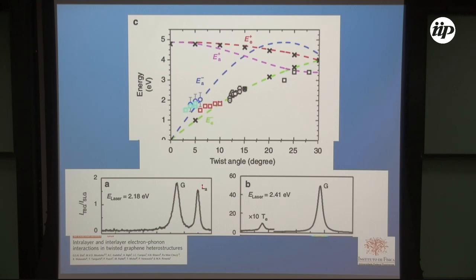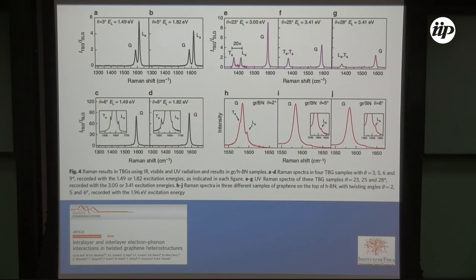So here, in this case, I have an LO phonon intralayer process. In this case, a TO phonon interlayer process. But you can have others also. My time is over, but I need to give you just one more case. When Eliel and Marcos did the calculation, they showed me, I said, well, that's very nice. But if this is true, now if you have graphene over boron nitride, you only see intralayer processes because you see only the process in graphene. So Eliel did the measurements for the boron nitride. The peaks are very small, but we can see only the intralayer process here when you have graphite over BN over graphite.